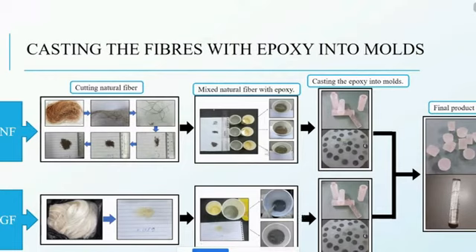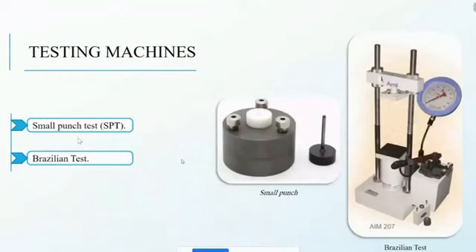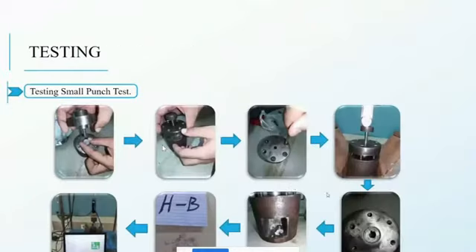So this is for the glass fiber. We did it as what we have done here, but it's only for 1%. For the testing, as I said before, this is the picture that we have for the small punch test, and this is the Brazilian that we used in our lab. Just to give more details about the small punch test, this is the picture of the setup that we manufactured in our lab.